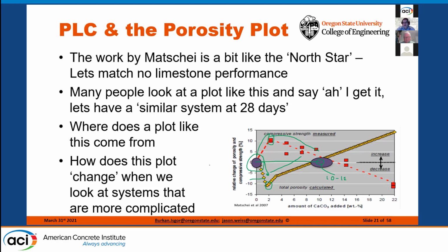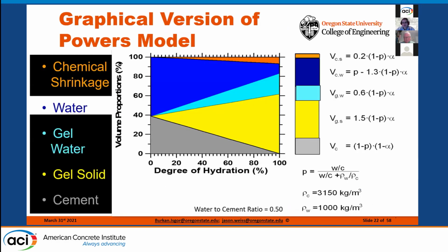So many people have used this plot and they've said, aha, what we're really after in North America is we want to get similar properties to a 150 cement with our 595 cement at 28 days. Now, what I want to do is take a step into where plots like this come from and see what happens when the system becomes a little bit more complicated, when we start adding SCMs into the system. So the whole drive behind this is we're going to really try to describe the porosity that's taking place in the system. Before I do that, I want to just get into Powers' model a little bit.